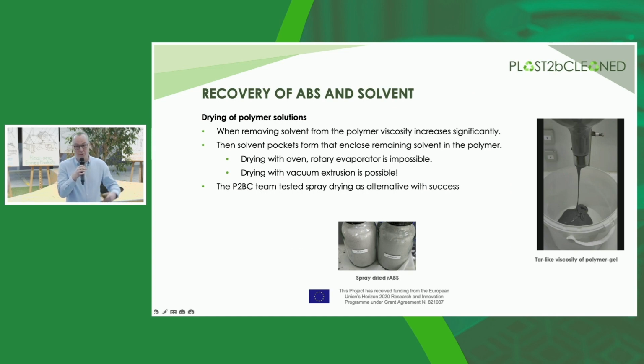Going to the next step. Once we remove the bromine flame retardants, we still need to separate the solvent from the polymer. And this is also not an easy task to achieve, because we chose the solvent because it has high interactions with the polymer. That means drying it, removing the solvent, is also quite tricky. When you think of traditional drying methods like using an oven or a rotary evaporator, you will see on the right-hand side, there should be a little video starting, that it's a very viscous gel-like material. We experienced that while drying, usually the outer layer dries up, and it forms sort of a solvent pocket, we called it, where the solvent still remains inside.